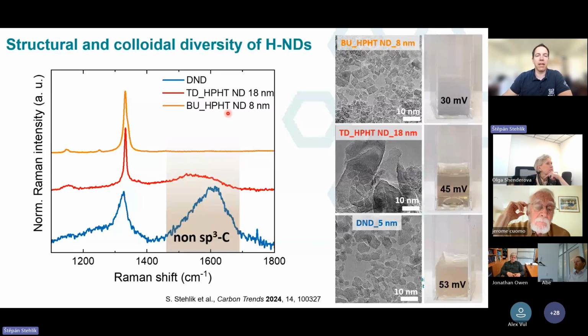But it was not only that. We also observed some dependence on the particle structure. You can see here that the magnitude of the zeta potential actually correlates with the particle structure and especially the non-diamond carbon content. These bottom-up HPHT nanodiamonds, as I have said, were about 30 millivolts. And from the Raman spectra, you can see that they are very pure. It's just diamond and some residual peaks from the CH bonds, actually. The top-down HPHT nanodiamond is still single crystalline, but it has already some sp2 carbon.